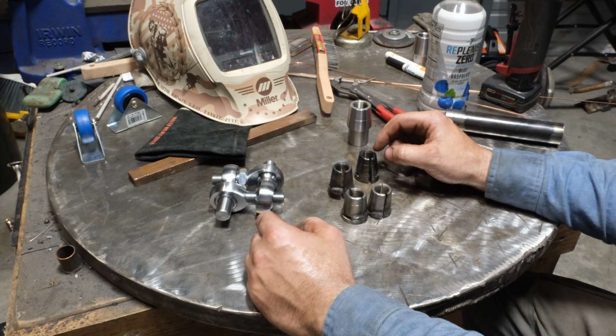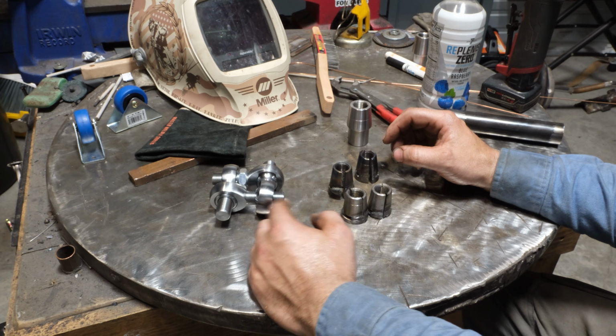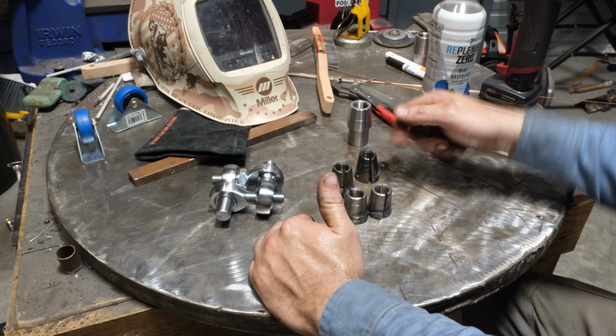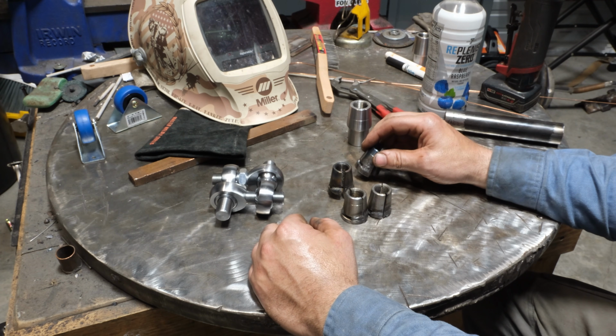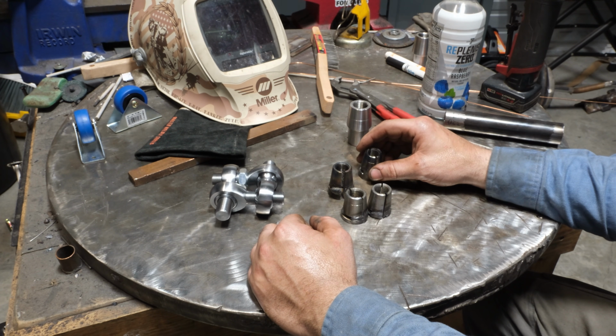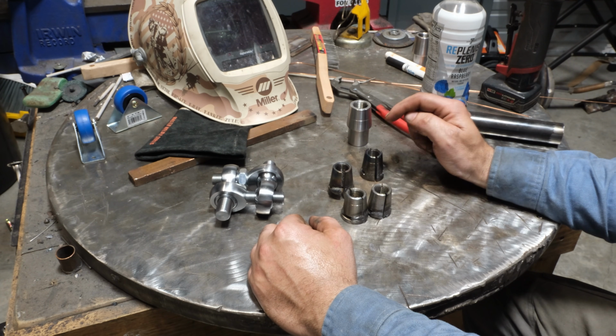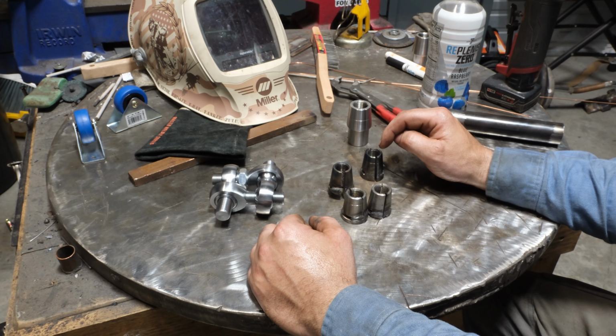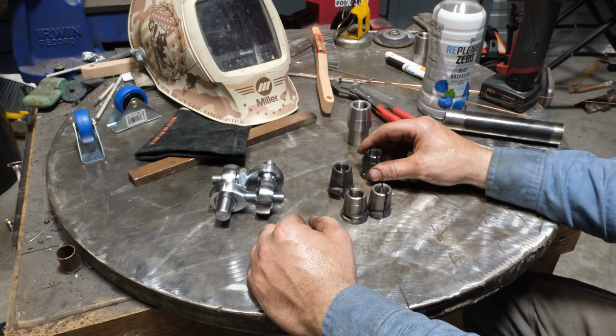And it really pays to set up little wheels or even have a buddy spin it slowly while you're welding to where you have minimal stops. If you can do this in 2 passes, or AKA a start and stop is half of it and then a start and a stop is the other half, it's highly recommended. The fewer starts and stops you have, the stronger the end result will be. And like I said earlier, avoid putting a bunch of tack welds on this. The fit should be good enough to where you don't need that, and that's just going to create lack of fusion.